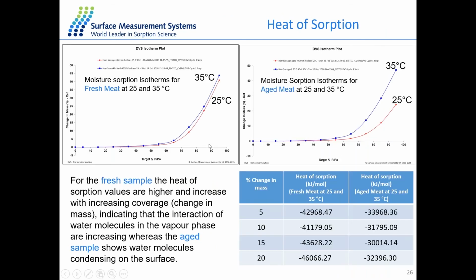Another parameter we can use for the prediction of shelf life is the heat of sorption. So to calculate the heat of sorption, we need to do the experiment at at least 2 different temperatures. So here we use fresh and aged meat samples at 25 degrees and 35 degrees.